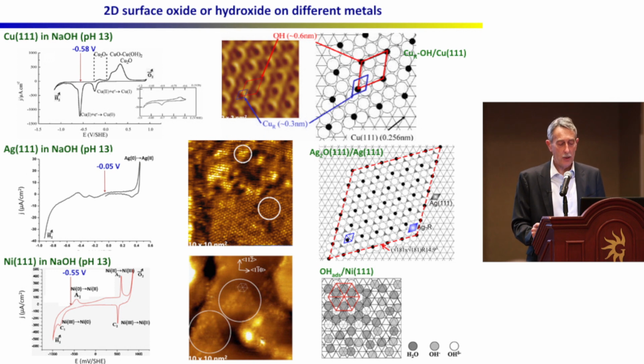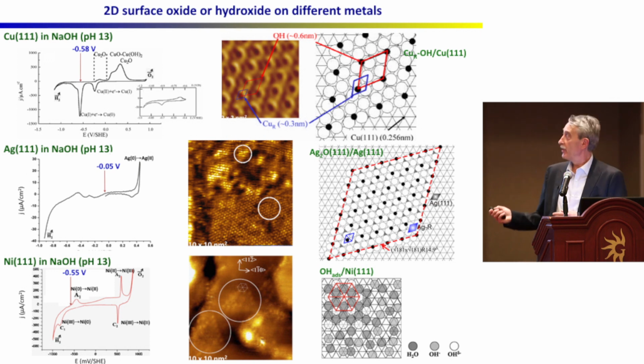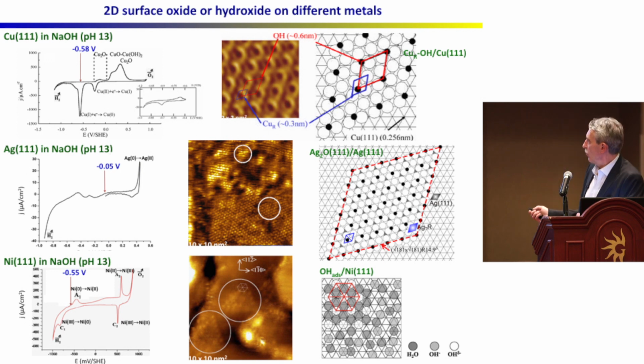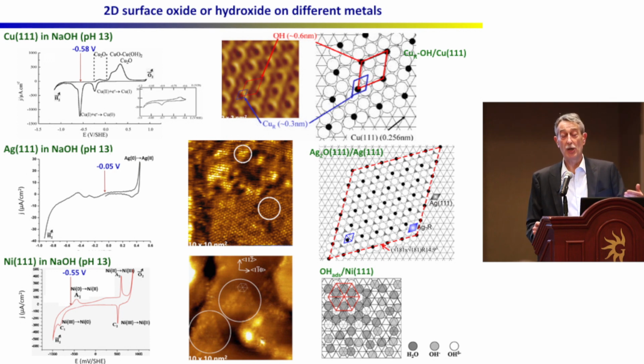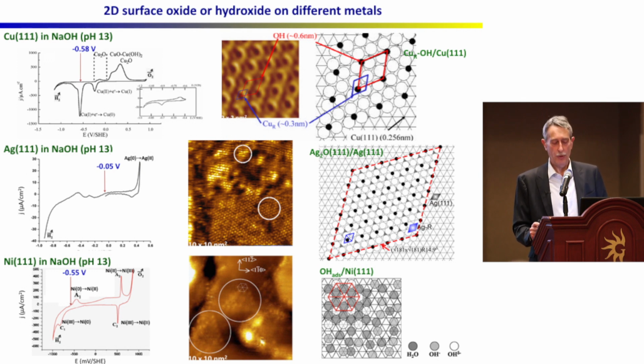And we did it also on nickel. And nickel is slightly different, because from these two we could think that it would be the same on all metals, but it's actually not the case. If you look at nickel, you have a structure which is not as well ordered. You have a local order here, and in other areas it's disordered. And we believe that this is due to the fact that we have only a partial charge transfer between the OH minus and the surface. So there are subtle differences between metals, but in all the cases you get a fairly well ordered structure.